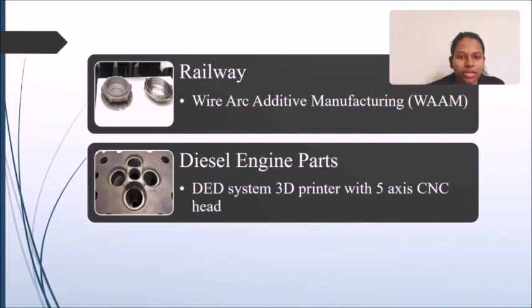And before using this 3D printing, they actually used to send their cylinder heads to machine shops to have the cracks removed and also to have the hole cold stitch welded, leading to a very long downtime. Even then, this was only a temporary solution for the problem because the cylinder heads would eventually crack again. This method was very ineffective, time consuming, and also very expensive.